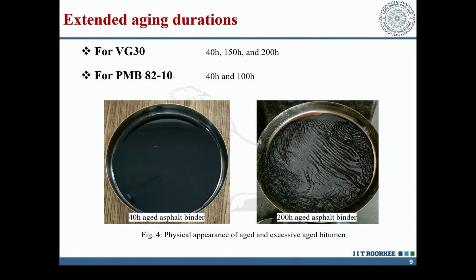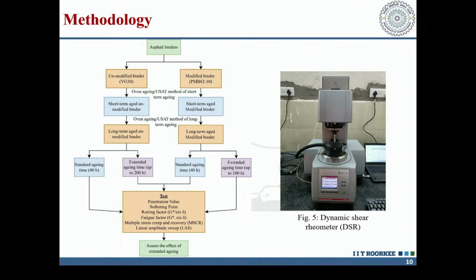So you can see here that for the extended aging durations, we have taken VG30 for 40 hour, 150 hour, and 200 hours. For PMB 82-10 rather, we have taken 40 hours and 100 hours. For the 100 hours of PMB 82-10, the similar condition of the aging comes in between 150 hour to 200 hour in VG30. So this is the methodology which we have taken.